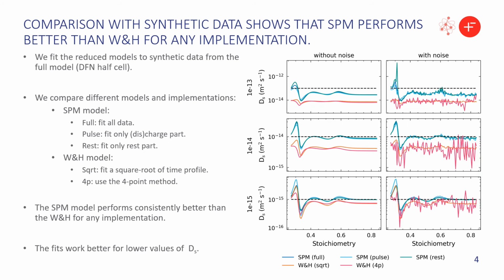And we also tested with noise. So we added some noise to the synthetic data. And what we find is that, of course, the more data we fit, the more robust the method is. So of course, SPM full does better than the pulse or the rest. And as we already knew, because we had experienced that in our previous work, the 4-point method is not very robust. So if we use the Weber-Huygens model, we actually want to use the square root approach.